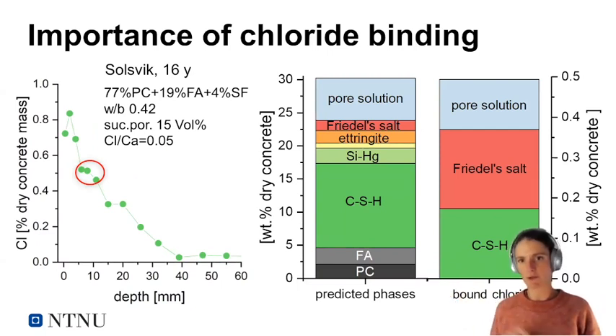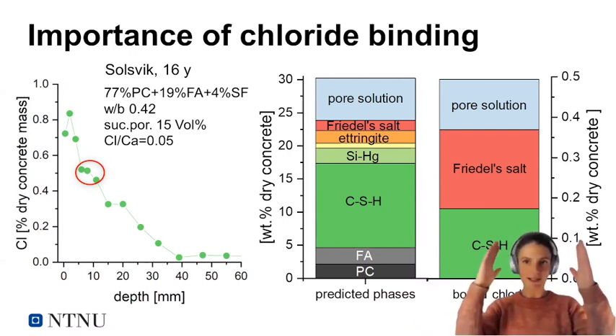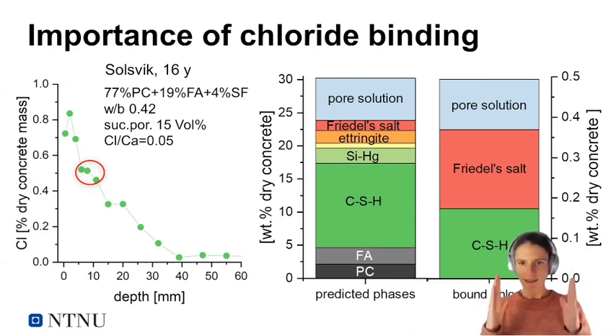Now, I put this red circle there because I want to focus on the chloride concentration at a depth of 10 to 15 millimeters, because these are cast beams, which means that at the surface, we have a higher paste content. We call this the wall effect. You can't have coarse aggregates where you have the formwork. So you have a higher paste content at the surface. And that makes it tricky because it's the paste that's binding the chlorides.